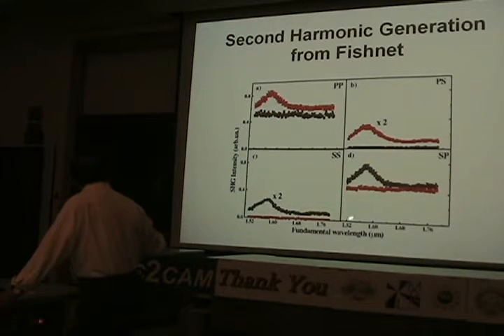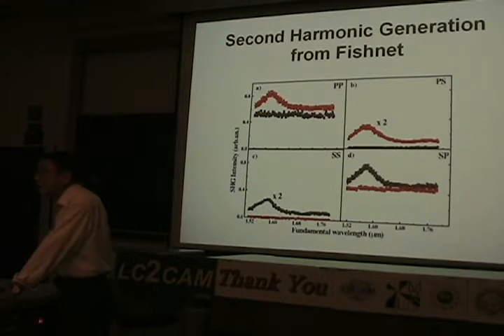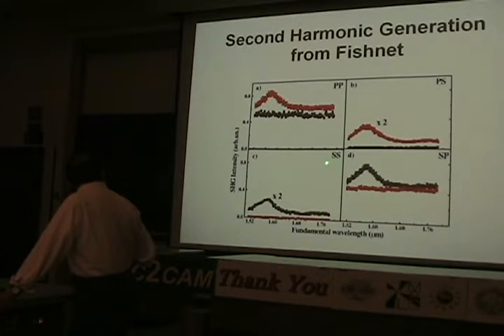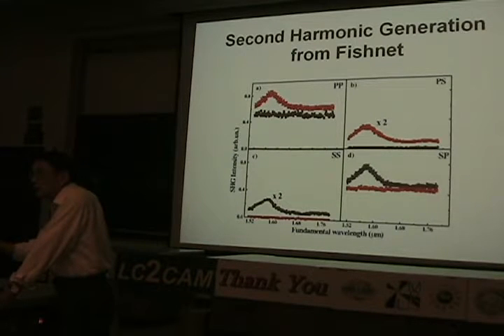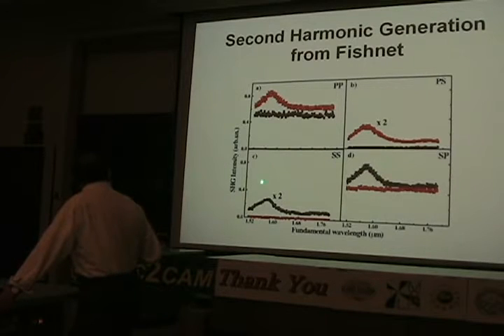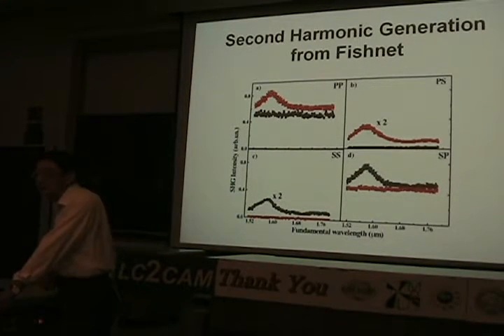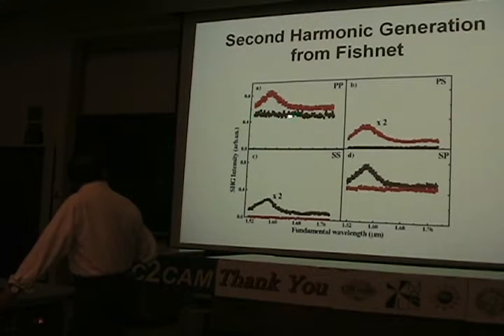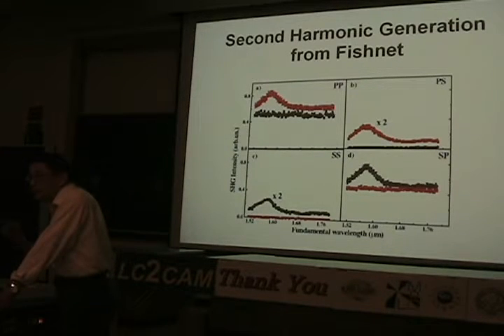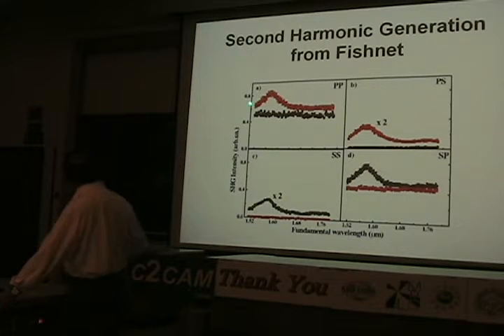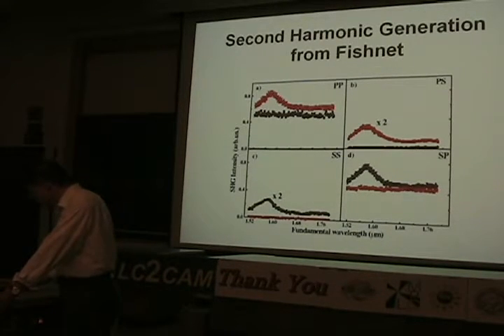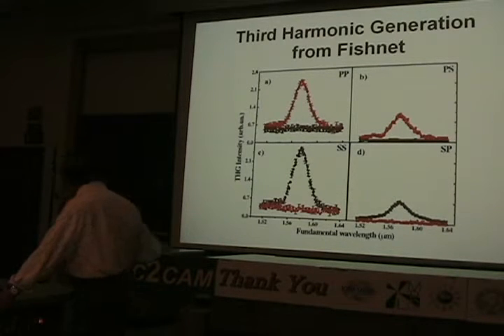Here, for example, the black curve, the flat curve here, is coming from a thin film of silver. And by symmetry, for S polarized in, S polarized out, or P polarized in, S polarized out, you will have no second harmonic generation by symmetry. But for our case, you can see the resonance at the magnetic resonance. For these polarizations, the thin film silver can still give you some second harmonic generation, but you see no resonance. But for the fishnet structure, you can see the resonance. And you can see the third harmonic generation easily. Again, you can see the resonant enhancement at the magnetic resonance.